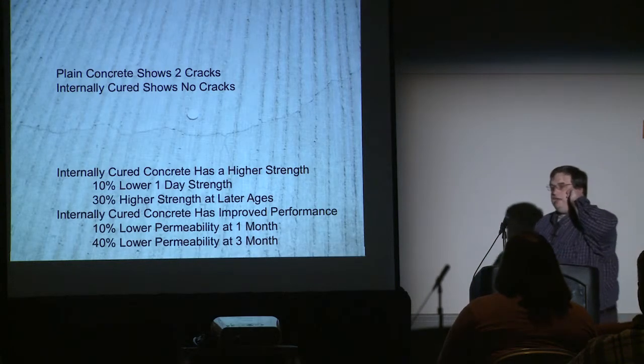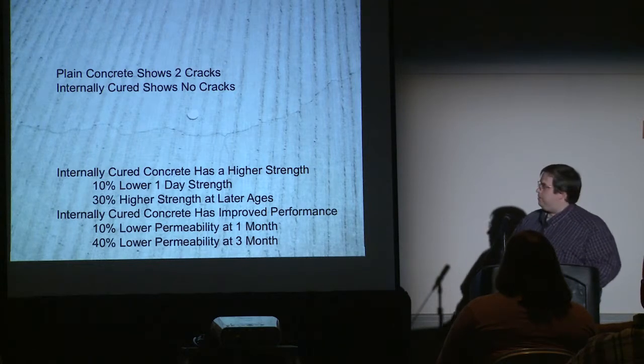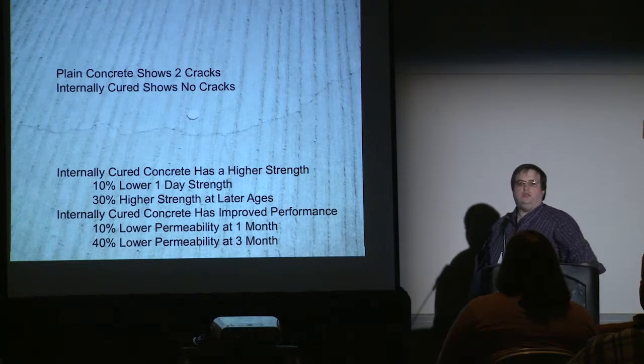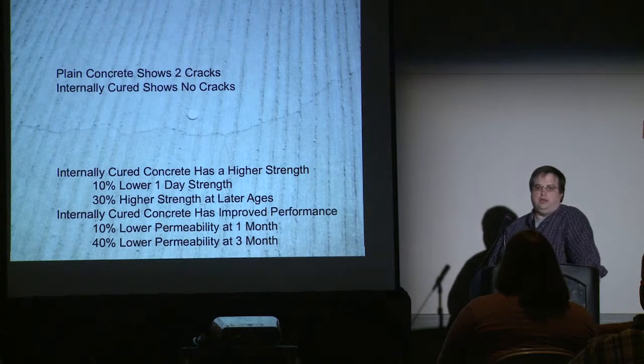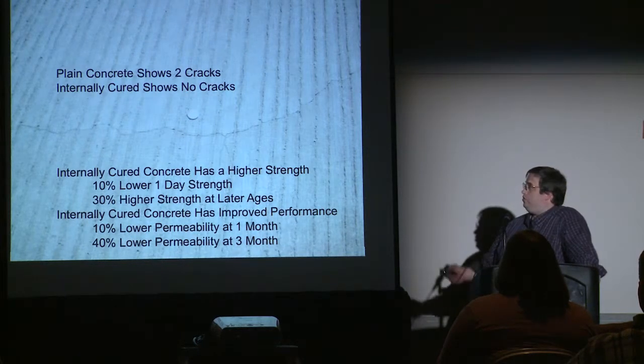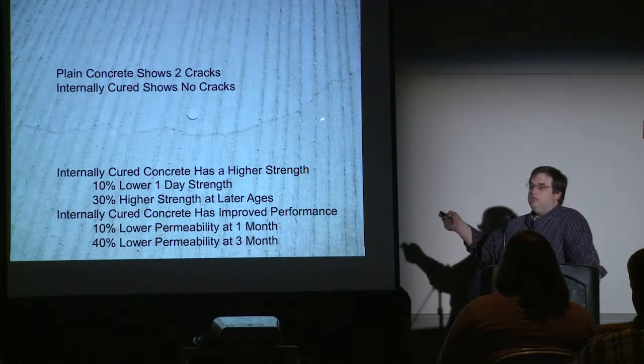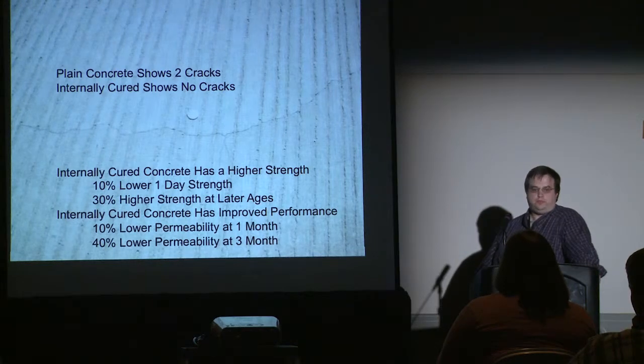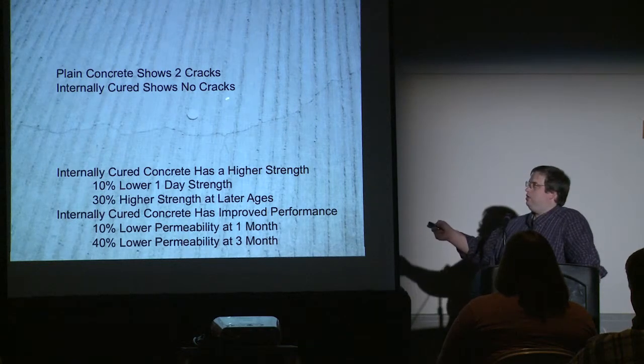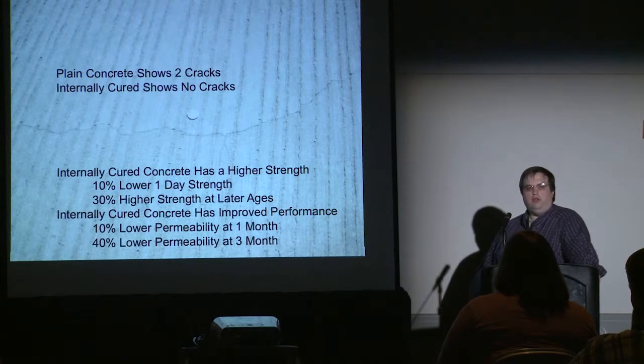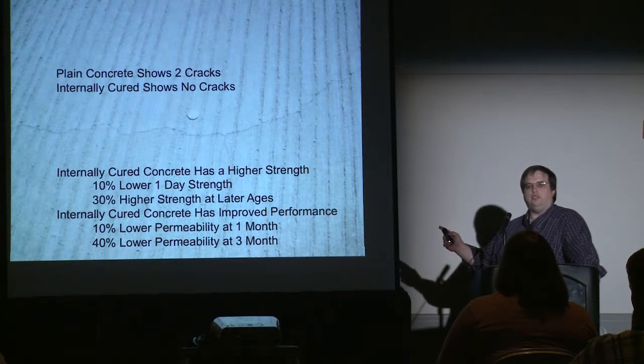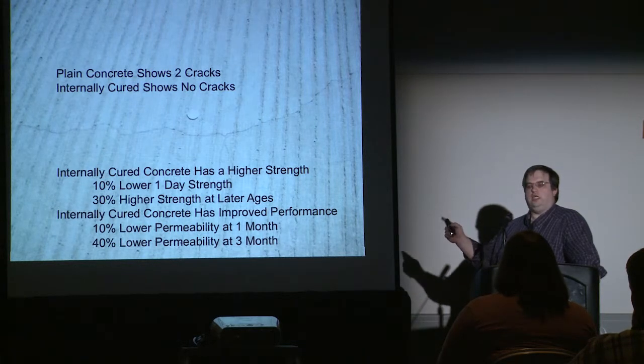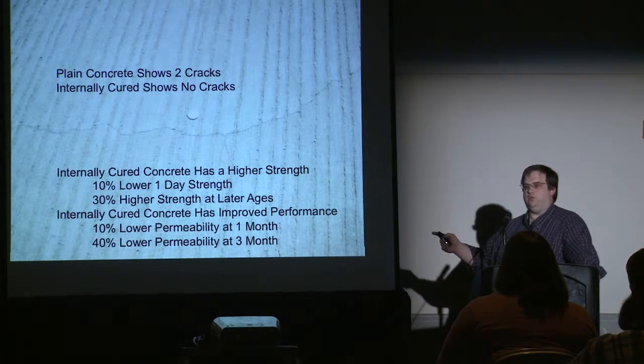And then we went back a year later and we looked at some of these decks. This is a picture off of the conventional INDOT approved mix design. It has two nice cracks that go right through the bridge. The internally cured one shows no cracks. Now, there are a lot of reasons that cracking can occur, but these are almost identical bridges, cast one day apart, the same construction crew, the same time, with the same materials. The only difference is one had internal curing, the other one didn't.